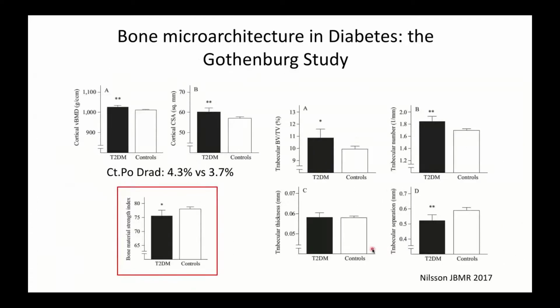The third study, the Gothenburg study by Nilsson, Lorentzon, and colleagues. So again, those guys confirmed that all the trabecular parameters are, if anything, better in type 2 diabetics than in controls. They also found better cortical bone volume. And when you say better cortical bone volume, well, it does not mean increased porosity. It means, if anything, similar or lower porosity. And in fact, in their study, cortical porosity was not different between controls and diabetics.